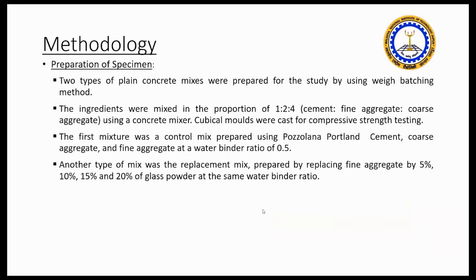This is the methodology. Two types of plain concrete mixes were prepared in this study using the weigh batching method, and the ingredients were mixed in the proportion of 1:2:4 using a concrete mixer. Cubical molds were cast for compressive strength testing. The first mixture was the control mix, which contained 0% glass waste, using pozzolana Portland cement, coarse aggregate, and fine aggregate at a water binder ratio of 0.5.